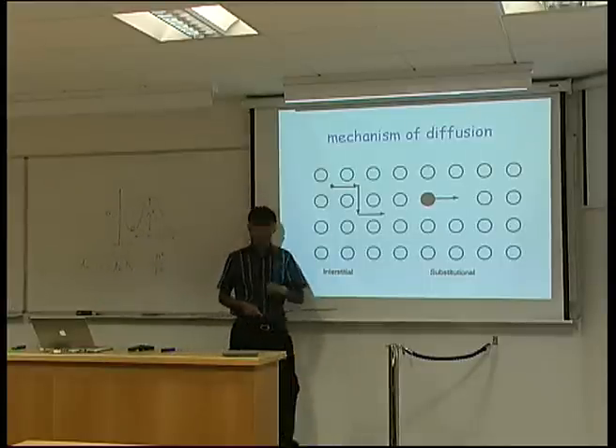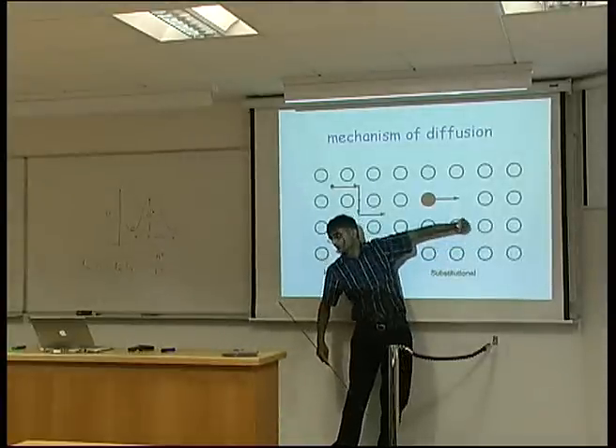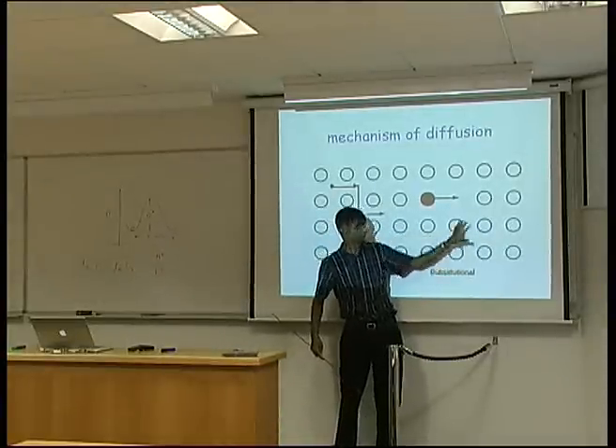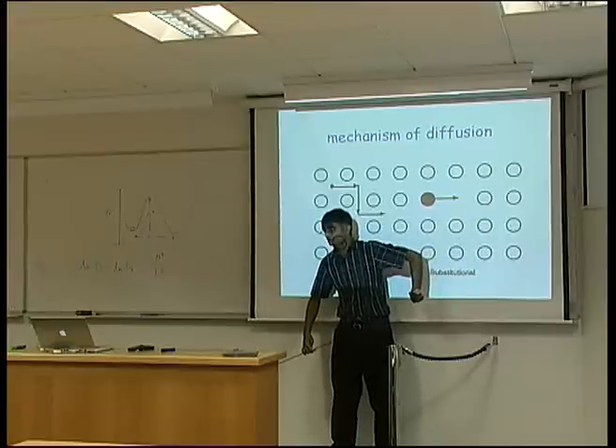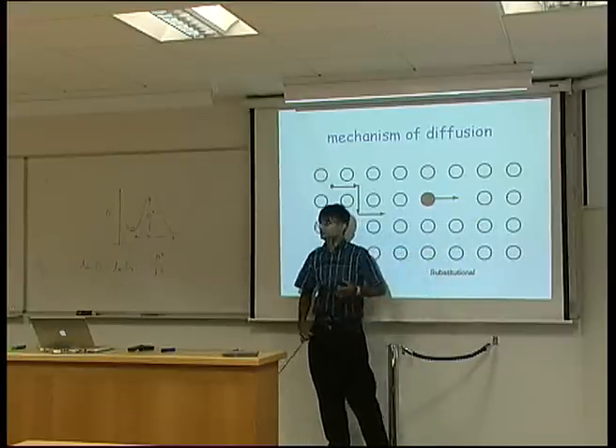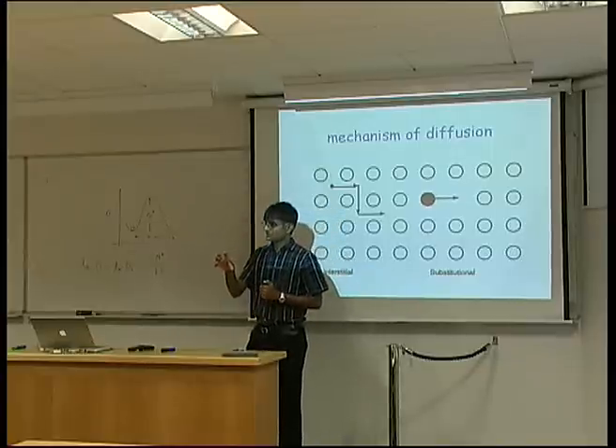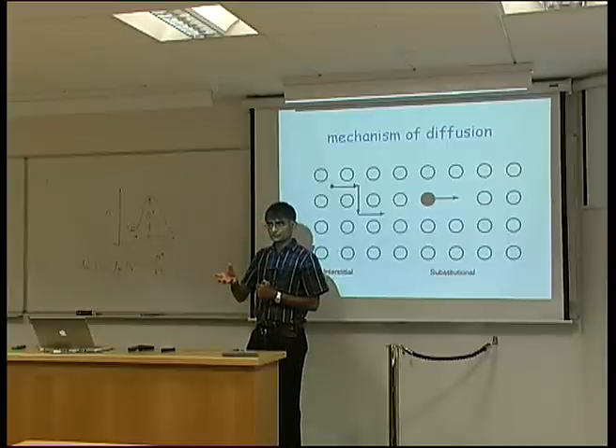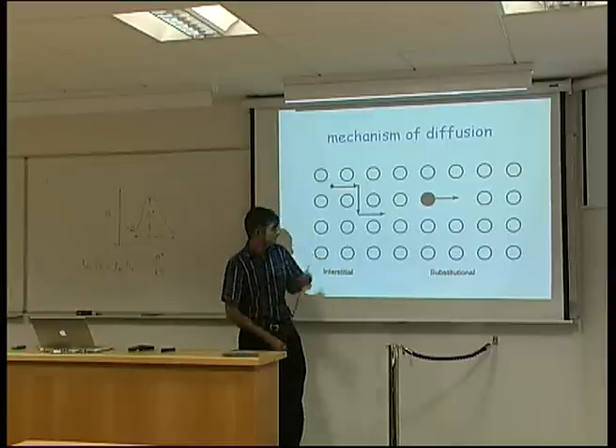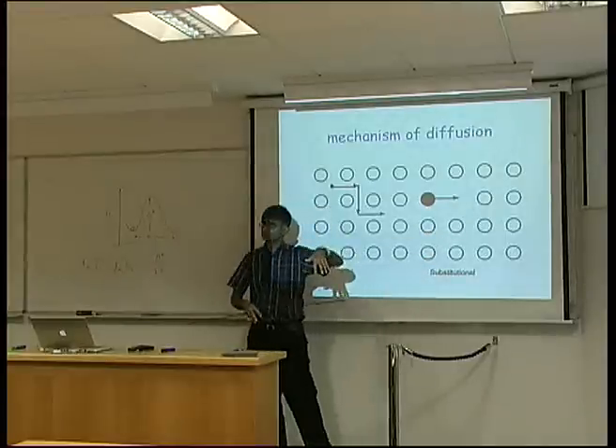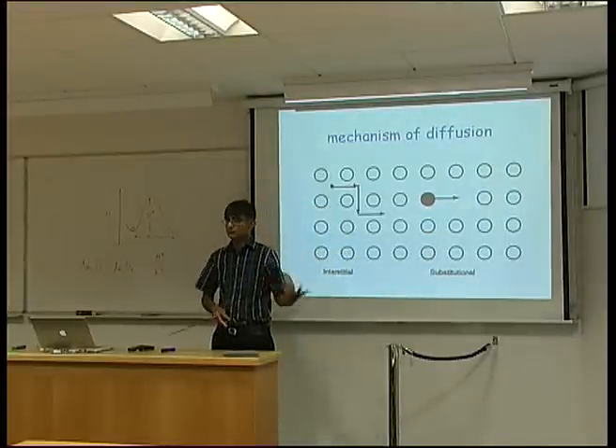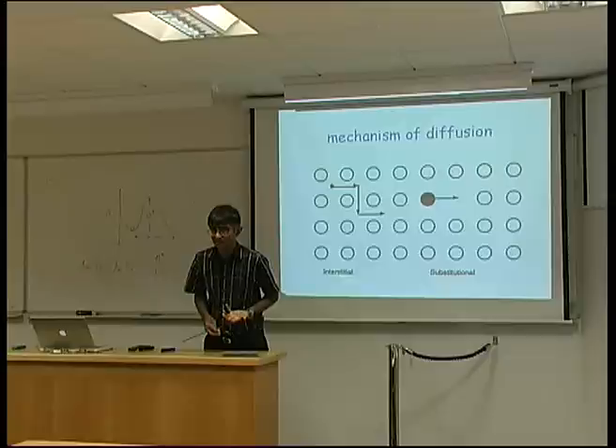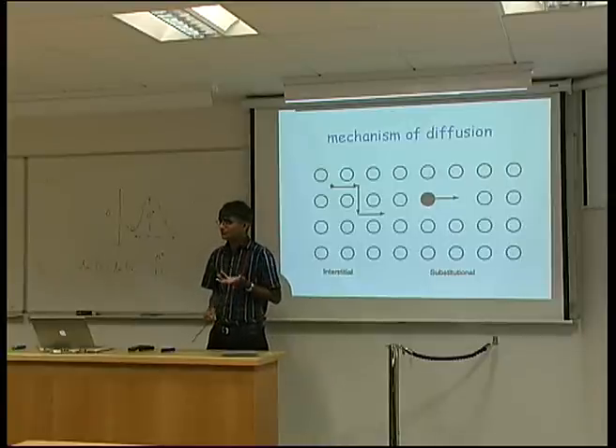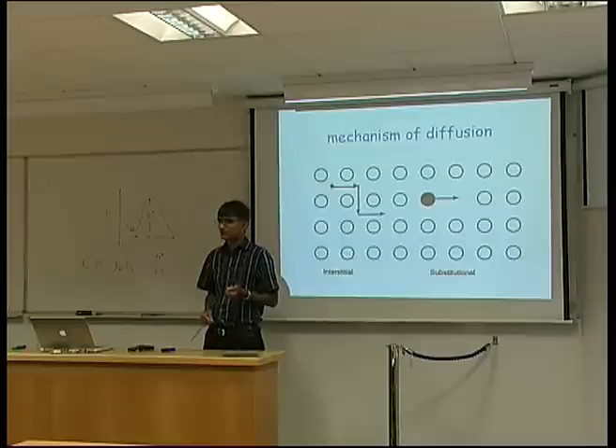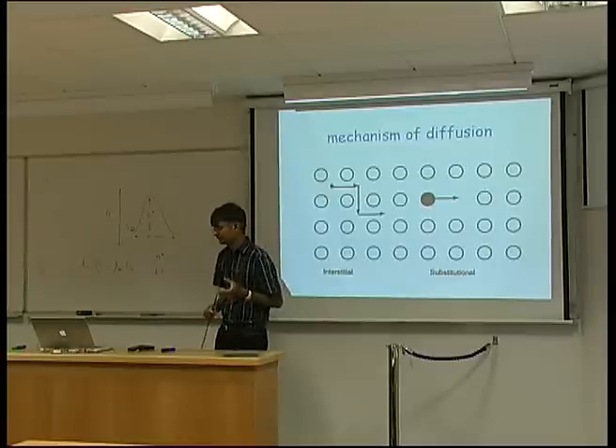Alternatively, you could reduce the distortions by making four atoms move together. Okay? If all four of them moved and swapped positions, then the distortions would be smaller. But then you require coordination between four atoms. And that's very difficult. To get four atoms to move in the right direction must be quite difficult. If I get a whole cluster of atoms to move together, the distortion becomes even smaller, but I require coordination between all those atoms. So, around the 1940s, there was huge disagreement about the mechanism of diffusion in the solid state, until